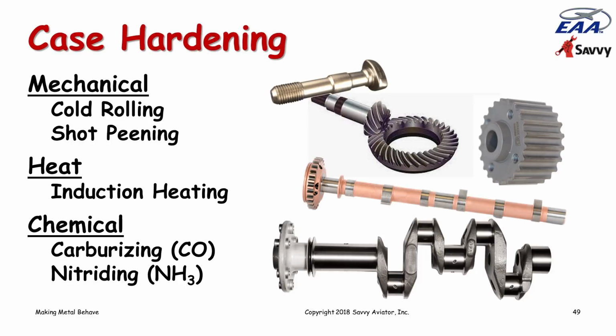And typically, when you carburize a camshaft, the hardened layer is maybe 15 thousandths of an inch thick, but it provides a very, very durable wear surface where we're interested in maximum hardness. The same sort of thing is done on crankshafts, where we want the journals, the polished parts that the bearings run on, to be as hard as possible.